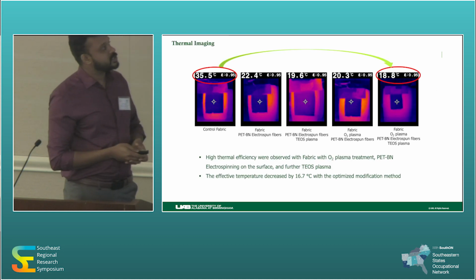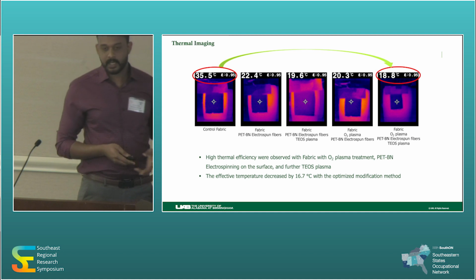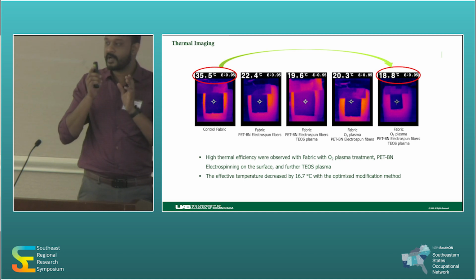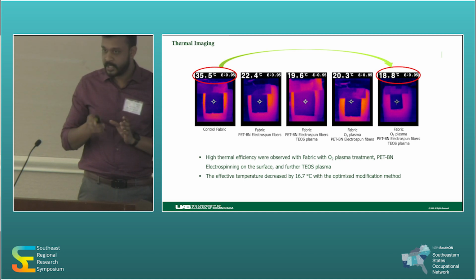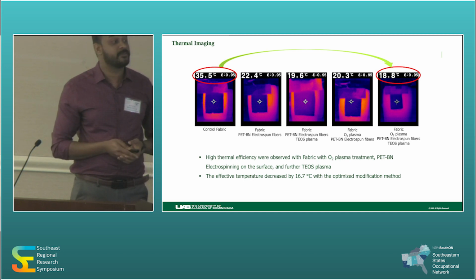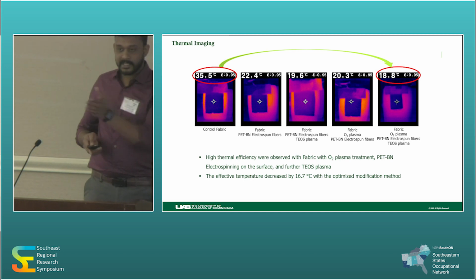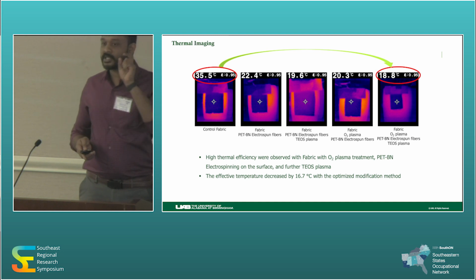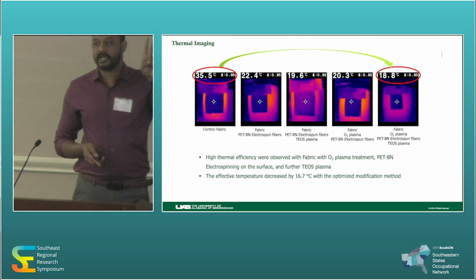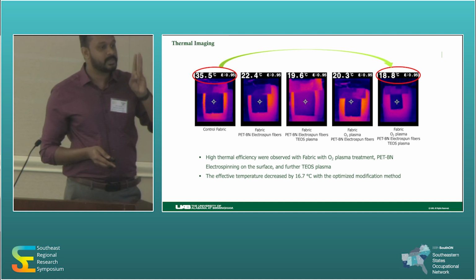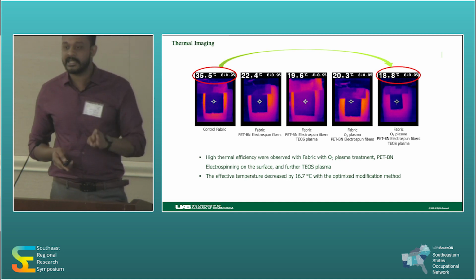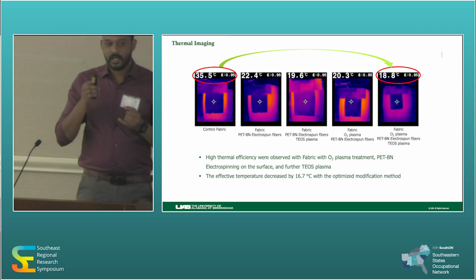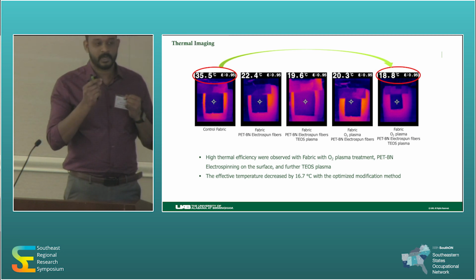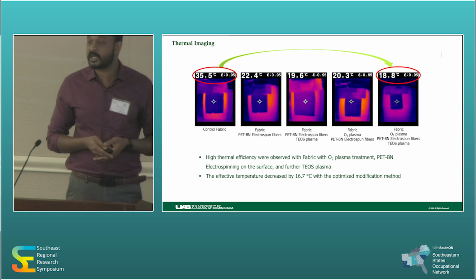So this is the thermal imaging data. With the control, we noticed that while we are providing a 40 degrees C platform, the effective temperature is 35.5. Then with the entire treatment at the end, with oxygen plasma, further electrospinning, further TEOS plasma, the effective temperature comes down to 18.8 degrees C. So we find the effect of boron nitride nanoparticle and silica nanoparticle. These two are working well.